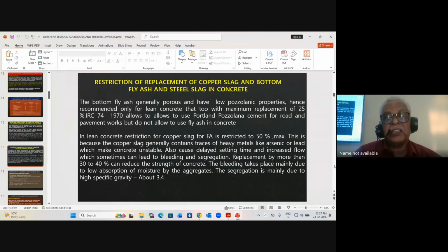In lean concrete, restriction of copper slag for fine aggregate is restricted to 50% maximum. This is because copper slag generally contains traces of heavy metals like arsenic and lead, which makes concrete unstable. It also causes delayed setting time, increased flow, and sometimes leads to bleeding and segregation. Their specific gravity is typically more than 3.2 to 3.4.